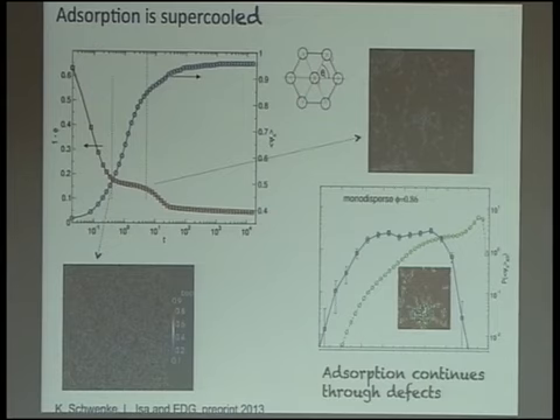Okay, good. So if I understood this right, you said that your surface tension actually becomes a function of the number of nanoparticles on the interface. But at least for very dense packings or jammed systems, I don't think this is quite a good description, because there are phenomena where you can stabilize non-spherical droplets with nanoparticles on them, like Pickering emulsions or bijels, whatever. So if it were just an effect of a reduced surface tension, then you wouldn't have them. So here I think, at least for the jammed case, it's much more the elastic properties which come from the jamming, which yeah, I think you're right.